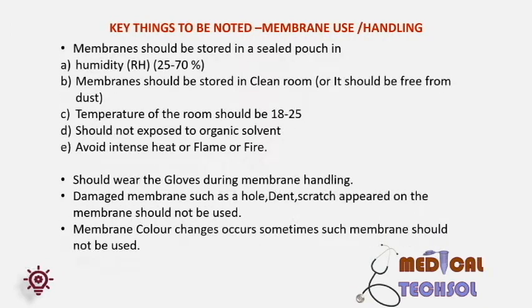Key things to be noted during membrane use and handling: membranes should be stored in a sealed pouch. Environmental conditions for storage are humidity 25 to 70% and room temperature 18 to 25 degrees centigrade. It should be stored preferably in a clean room, free from dust or particles. It should not be exposed to organic solvents, as organic solvents change the chemical properties of the membrane. As nitrocellulose membranes are flammable, avoid fire, intense heat, or flame.